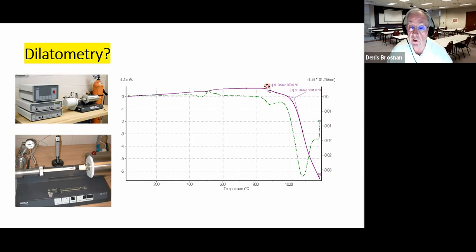You'll also learn later in this course that the incipient vitrification, the first amount of shrinkage, takes place when the lowest melting glass melts in the ceramic. So that's probably going to be a very high alkali glass in a vitrified clay ceramic. And then as we get to higher temperatures, a second glass, which contains a greater amount of alumina because alumina was dissolving in the glass during this period, will vitrify here. So the shape of the curve and the derivative curve, which tells us when things are changing, meaning incipient fusion where the derivative goes negative, and the second point of fusion when the derivative goes even more negative, tells us about the shrinkage.